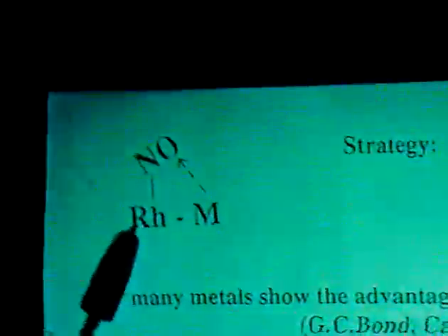So for enhancement of NO dissociation, our strategy is, at first, to use bimetallic sites composed of rhodium and an oxophilic metal. For the adjacent site, rhodium and the second additive, these oxophilic metals, then the oxophilic metal catches the oxygen atom of the NO molecule adsorbed on the adjacent rhodium site.